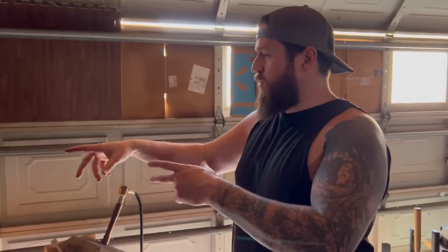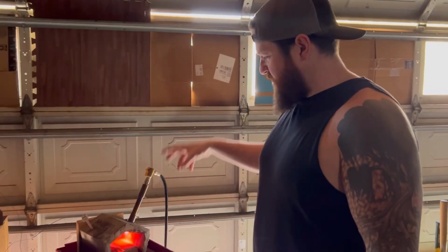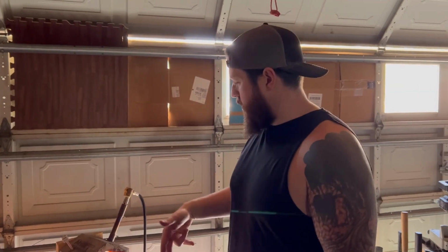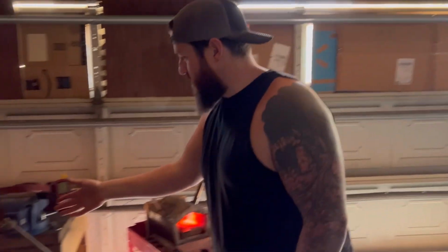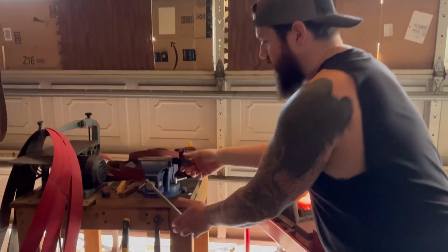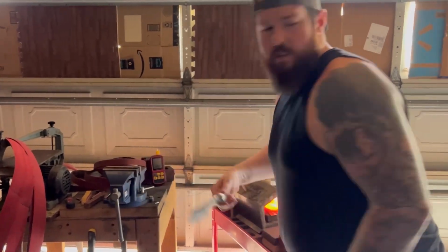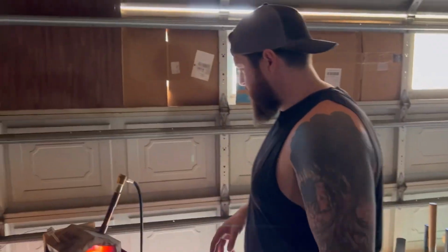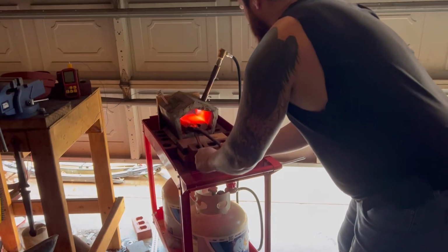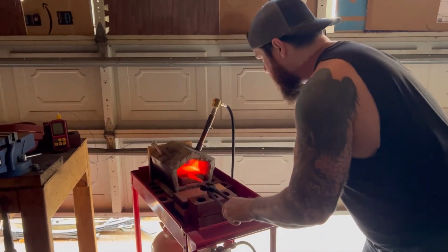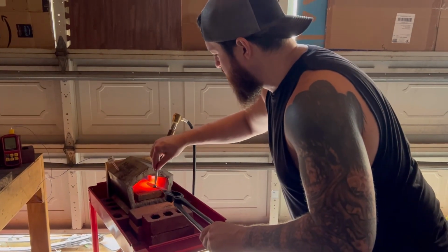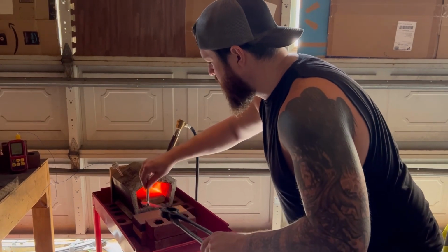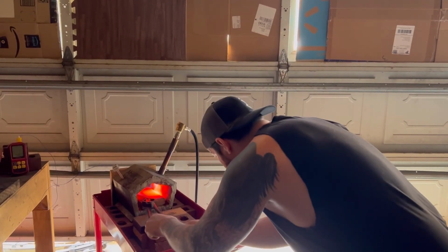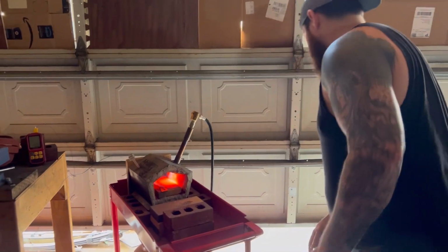All right, so it's cooled. We've already got it back in the forge. We're bringing it up to temperature, and we're going to quench it here in just a second. Let's see if this is cooled off enough to get this out of here. Those have already quenched. This one's just about ready. What I do is I get it out and check it with my magnet. Magnet's not sticking, so that's good. It's still sticking here, so it needs just another minute to get that part of it hot.